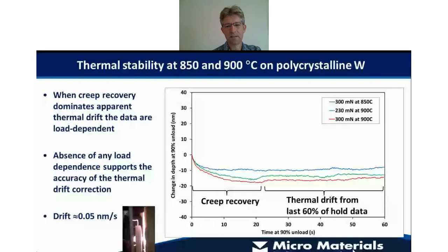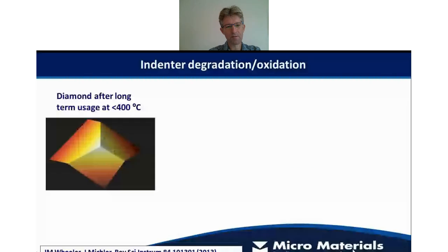So in these examples here, typically the drift's about 0.05 nanometers per second, which is not quite as good as room temperature, but it's certainly good enough to do high temperature tests. And there's a little picture in there from a high temperature system at Oxford University, and you can see there that the tip glows at high temperature. So you've got heating on both sides of that contact.